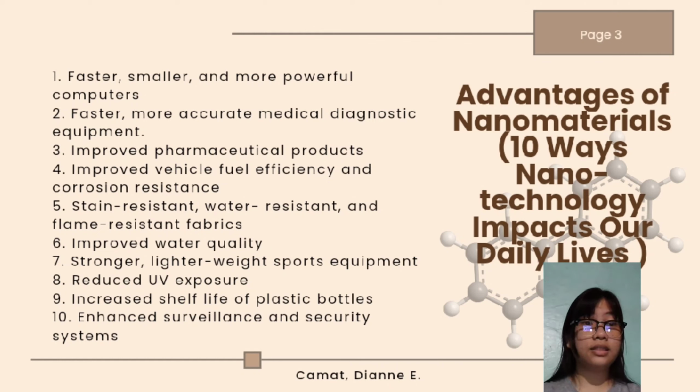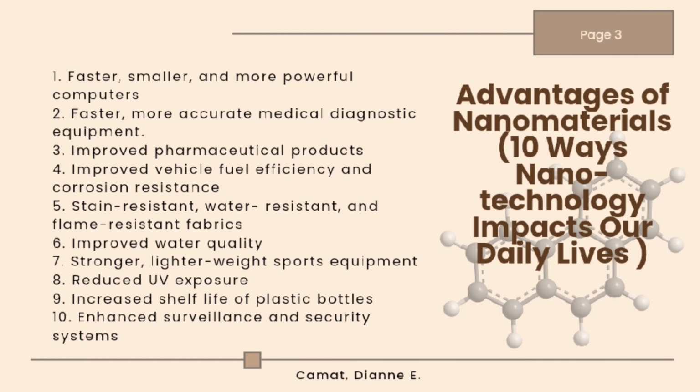Nine, increased shelf life of plastic bottles. Many drink bottles are made from plastic containing nanoclays, which increase resistance to permeation by oxygen, carbon dioxide, and moisture. This helps retain carbonation and pressure and increases shelf life by several months.